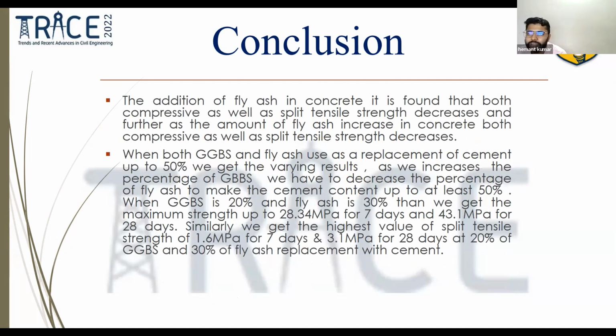When both GGBS and fly ash are used as a replacement of cement up to 50%, we get a varying result. As we increase the percentage of GGBS, we have to decrease the percentage of fly ash to keep the cement replacement up to at least 50%. When GGBS is 20% and fly ash is 30%, then we get the maximum strength of 28.34 megapascal for 7 days and 43.1 megapascal for 28 days. Similarly, we get the highest value of split tensile strength of 1.6 megapascal for 7 days and 3.1 megapascal for 28 days at 20% of GGBS and 30% of fly ash as a replacement for cement.